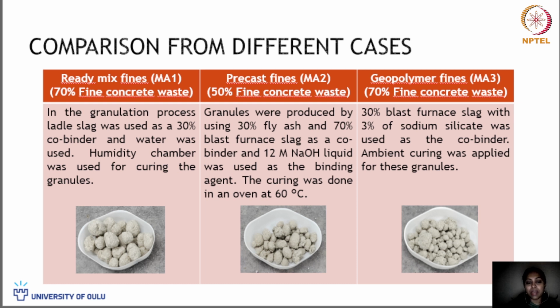In this granulation of MA1, we used ladle slag of 30% as co-binder, and we just used water and a humidity chamber. I mean, there is also a possibility to use a carbonation chamber, which will improve the environmental impact positively. And in the precast fines, we used 50% co-binder, of which 30% is fly ash and 70% is blast furnace slag. And we also used 12 molar sodium hydroxide liquid and cured at 60 degrees Celsius. And in the third one, for the geopolymer fines, we again alkali activated with 30% of blast furnace slag and 3% of sodium silicate and cured at ambient temperature.